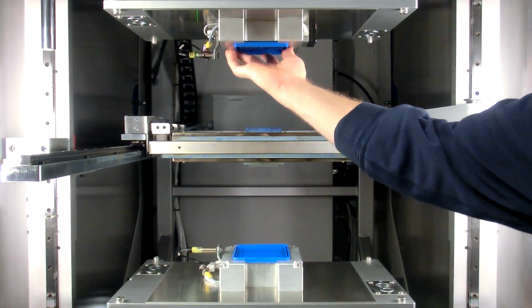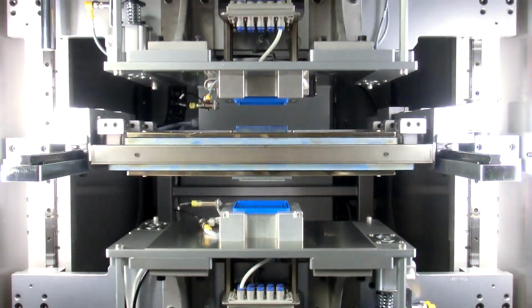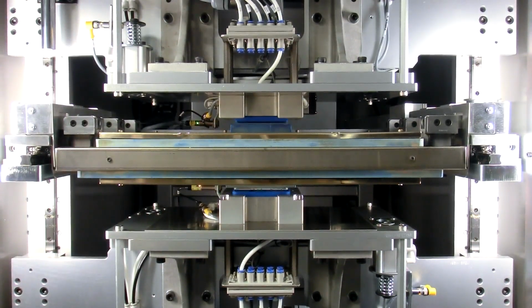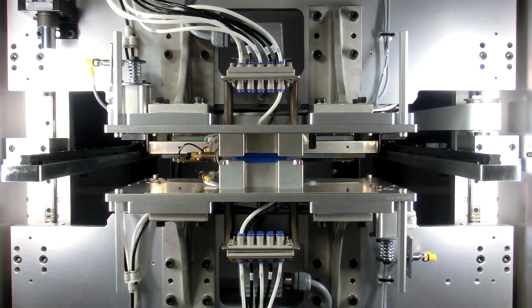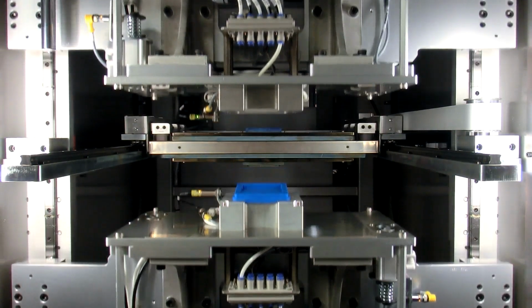Polypropylene? Yep, this is a polypropylene part. The heated tool here is probably around 800 degrees Fahrenheit. It's a quick melt time because of the high temperature. And then this is the seal phase where we're pushing those plastic parts together to get a bond.